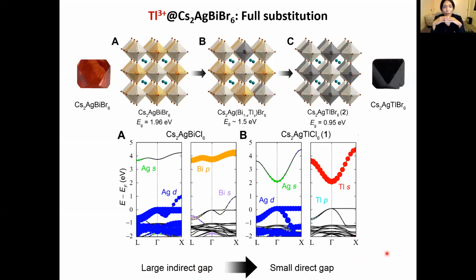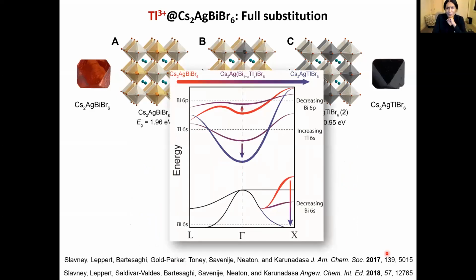So when we replace bismuth with thallium, we do 2 things. One is we add thallium, and the other is we are removing bismuth, right? You don't need a PhD to say that. So it turns out that adding thallium changes the conduction band, and removing bismuth changes the valence band. So we try to show it in the schematic.